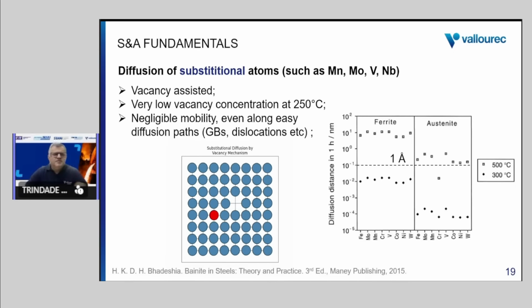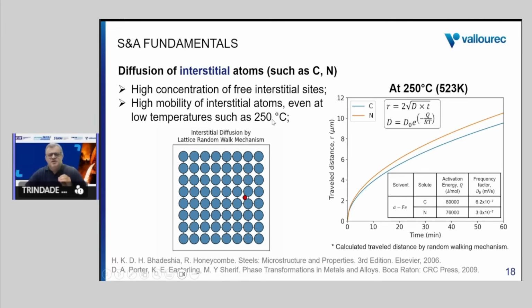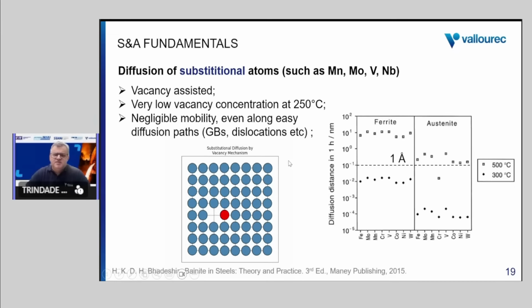The second point is, if you analyze the diffusion of substitutional elements, like manganese, molybdenum, vanadium, niobium, for example, at 250 degrees Celsius the mobility is almost nothing in terms of diffusion distance. After 1 hour at 250, the diffusion distance, here we have data from literature, 300 degrees Celsius and 500 degrees Celsius, in the ferrite will be around 1 angstrom. So it's nothing. What I want to tell you is that during aging, most probably the substitutional elements have absolutely nothing to do with aging, but only the interstitials, because they indeed have the ability to travel, to diffuse up to the dislocation core and saturate it, okay?